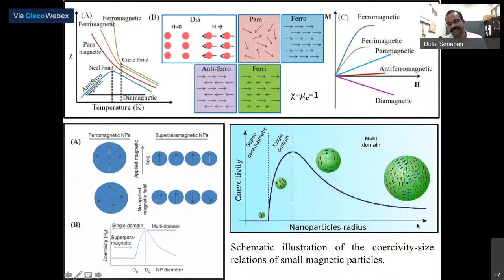The interesting thing is when we make a nanoparticle and reduce its dimension, and we measure the coercivity. Coercivity is the resistance to changing magnetization, which means they are magnetically stable. Once we reduce the dimension from a bigger particle to a smaller particle, we reach a dimension which we call the critical dimension. That has the highest coercivity, or it has a single domain where magnetization is very difficult to change. But once we reduce the dimension further, the coercivity decreases fast and goes to almost zero.